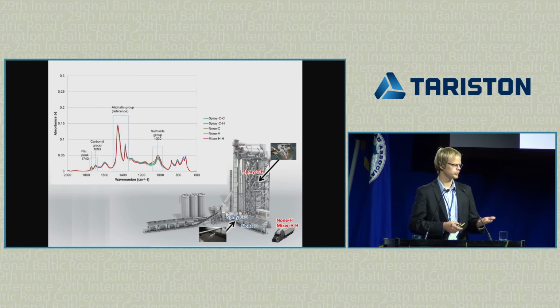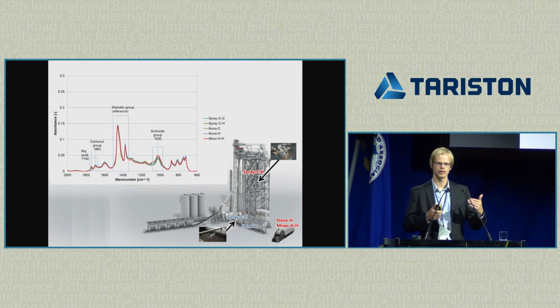And finally, Professor Zovka already explained the Fourier transform infrared spectroscopy. This is what we use to evaluate chemically the differences. And these are the 2 functional groups, as he explained, that represent aging of the binder. So the sulfoxide group and carbonyl group are the ones that increase. The area below the curve increases when the material ages. So, as I said, we didn't see any reduction of these areas. That's because we cannot really rejuvenate, we cannot restore the chemical structure of the aged binder.